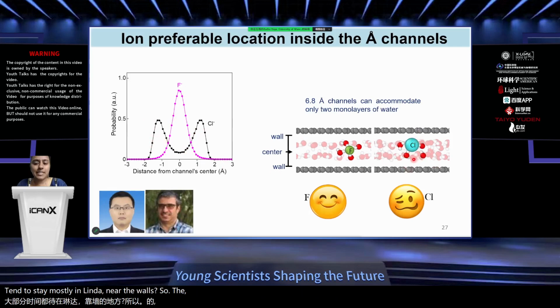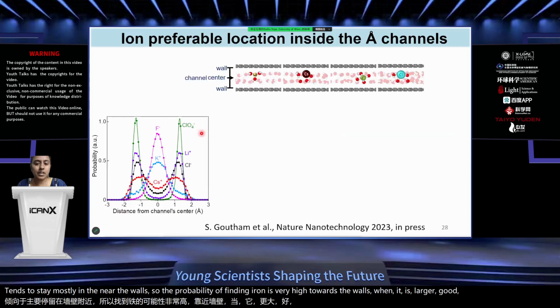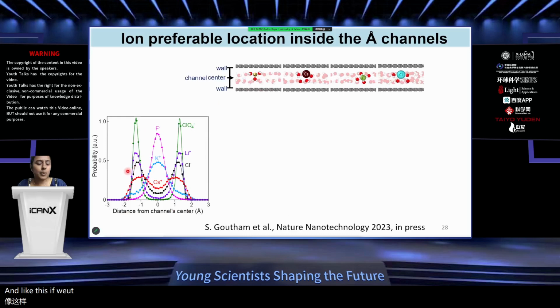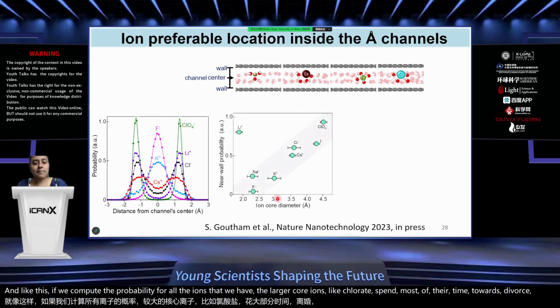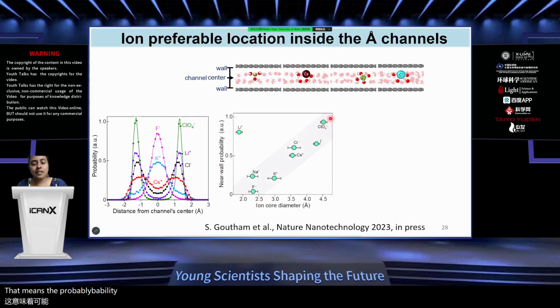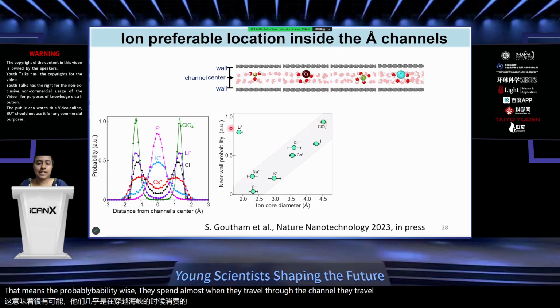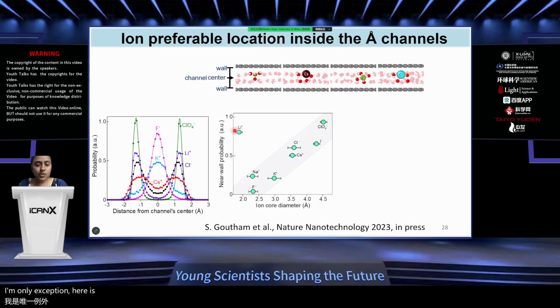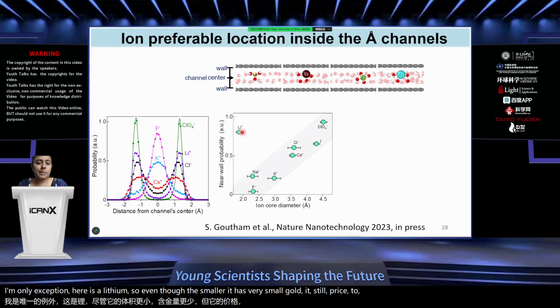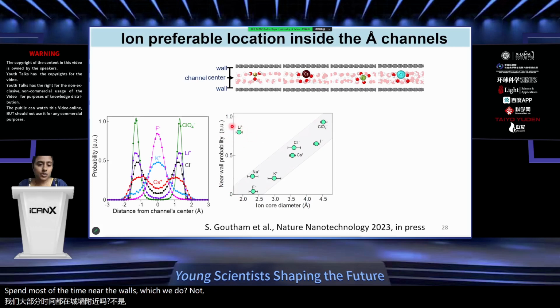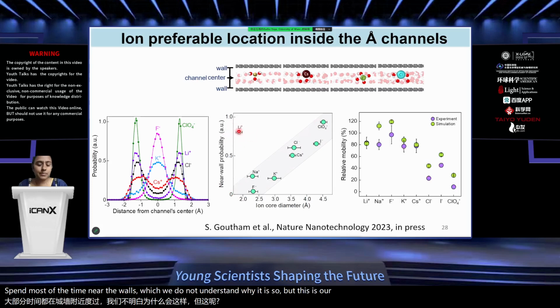So the probability of finding the ion towards the walls is very high when it has a larger core. If we compute the probability for all the ions that we have, the larger core ions like chloride spend most of their time towards the walls. That means when they travel through the channel, they travel along the walls. The only exception here is lithium. Even though it has a very small core, it still spends most of the time near the walls, which we do not understand why, but this is our observation.